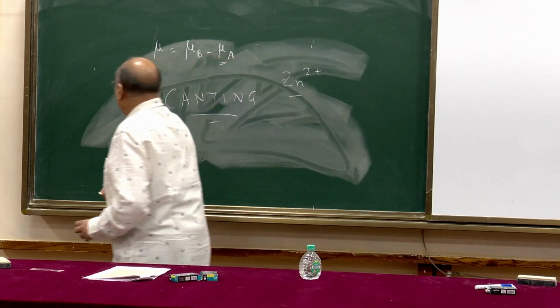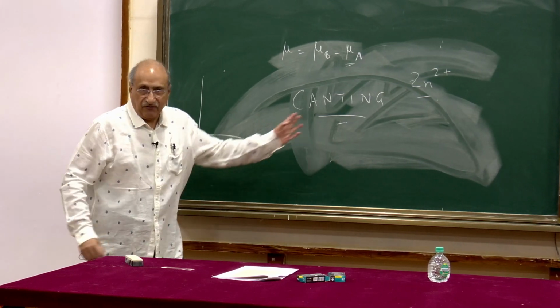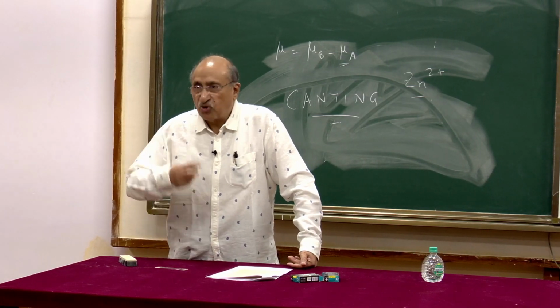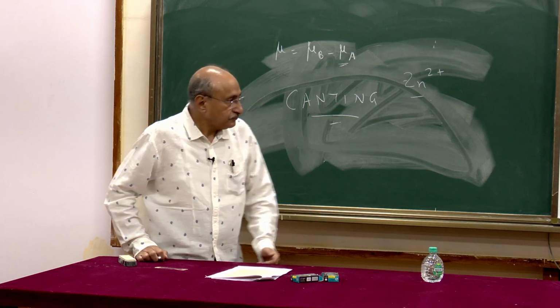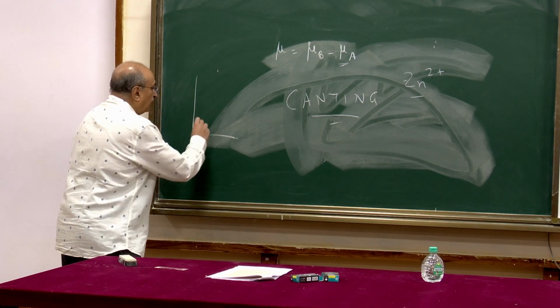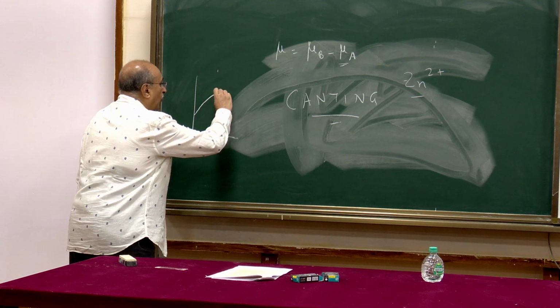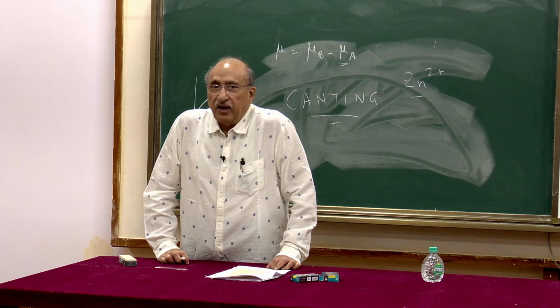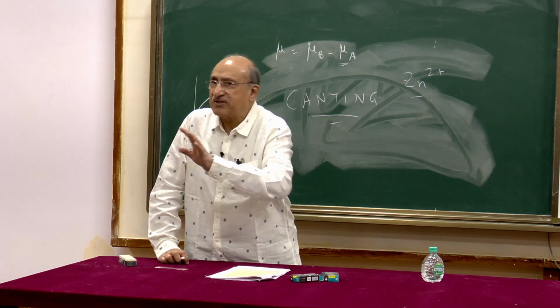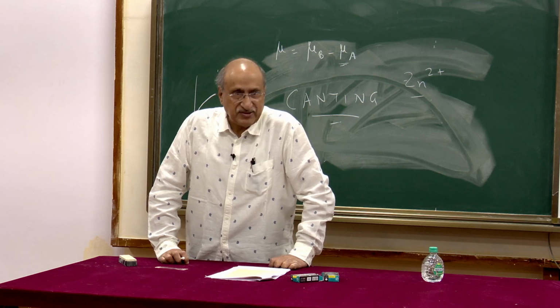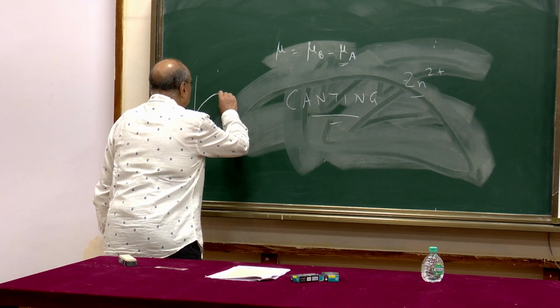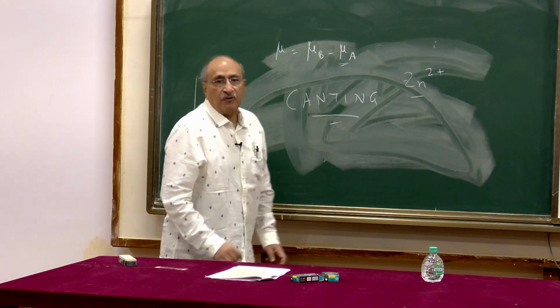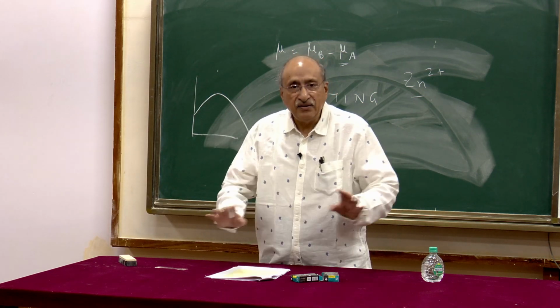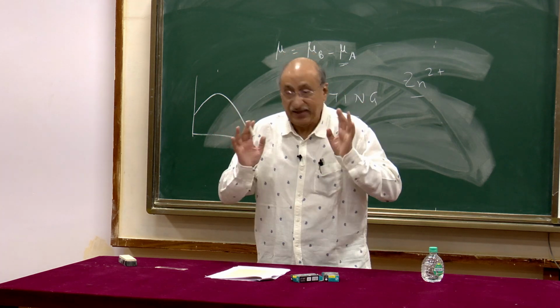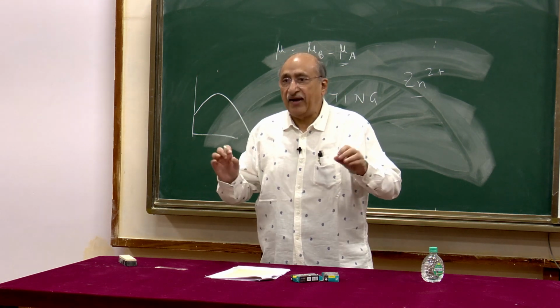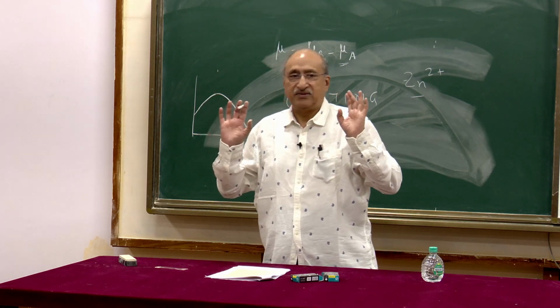So what you find, if you plot, in fact I will give you the actual plot in tomorrow's class because I have worked on this particular problem quite a bit, so my tomorrow's lecture will be essentially based on this idea. If you have a ferrite and you keep on adding zinc, you will find initially the magnetic moment will go up, and around 40 to 50% when the A site is filled with zinc 2+ ions, it will start reducing. And for pure zinc ferrite, again it will become 0, because if it's purely zinc ferrite, the A side is completely filled with zinc ions and there is no magnetic ion on the A side.